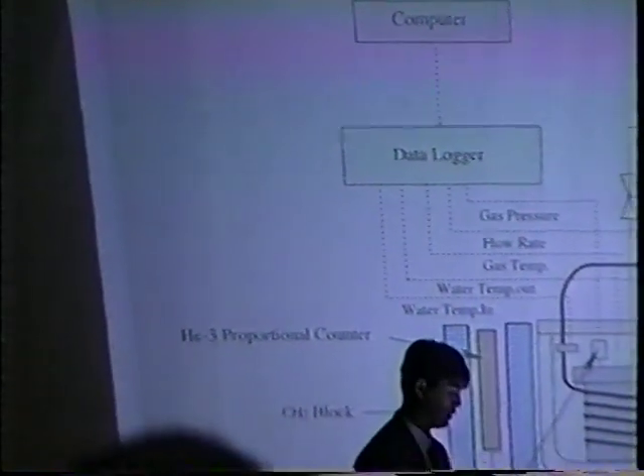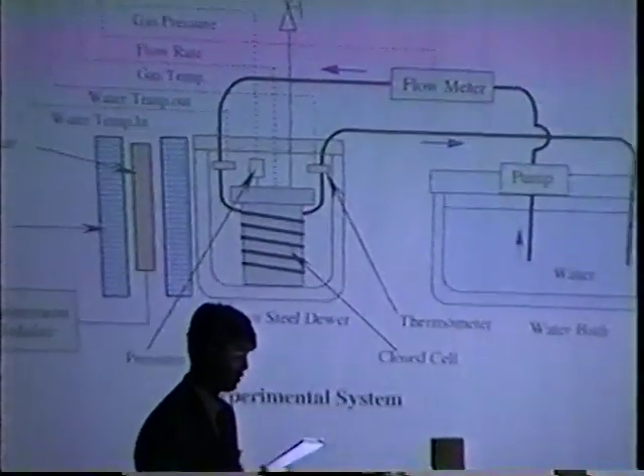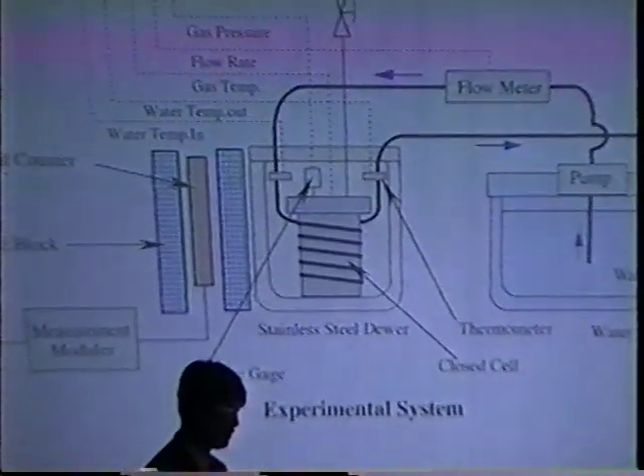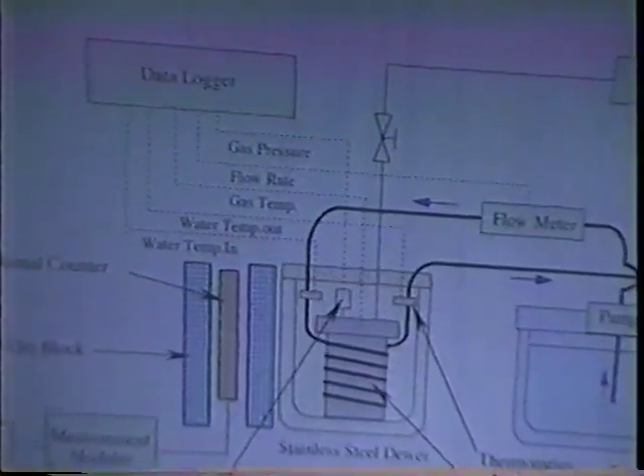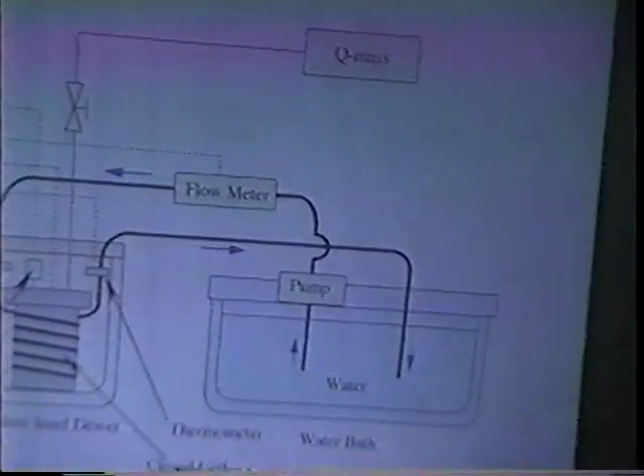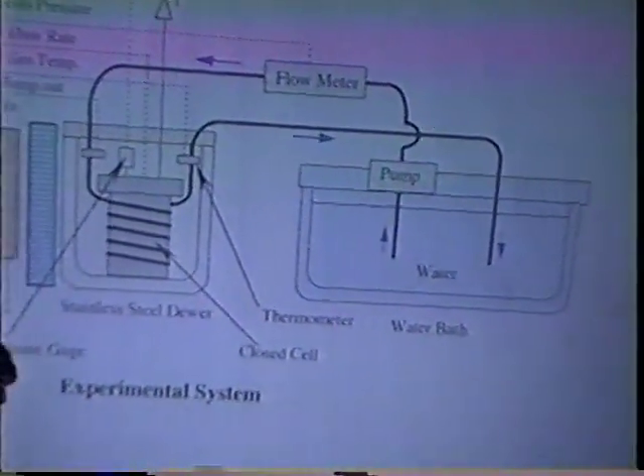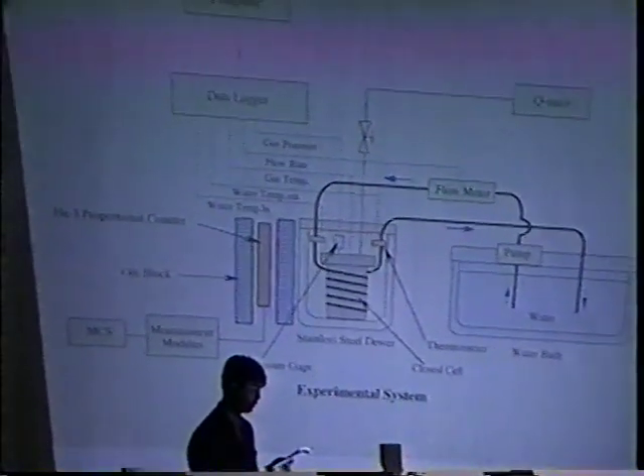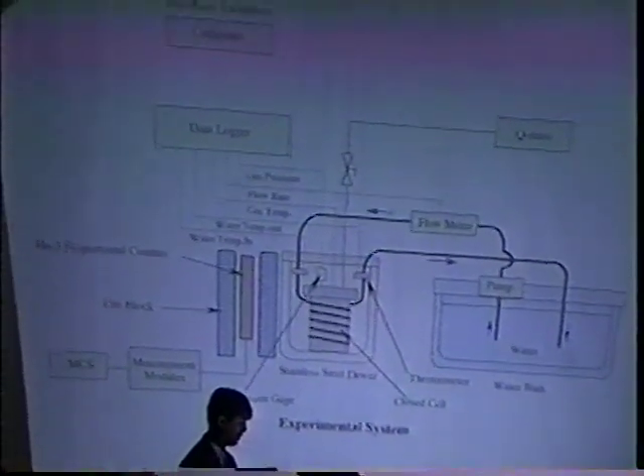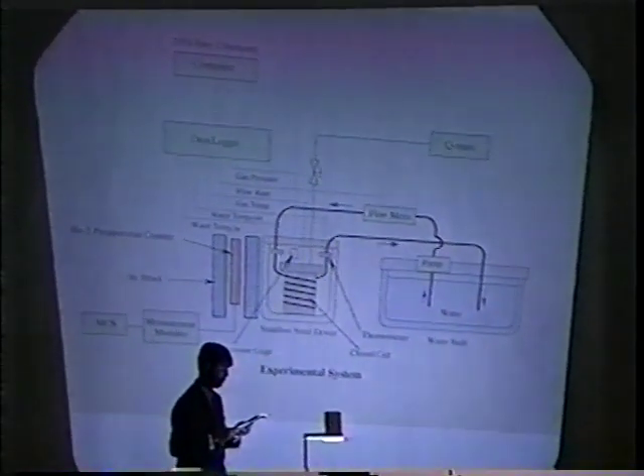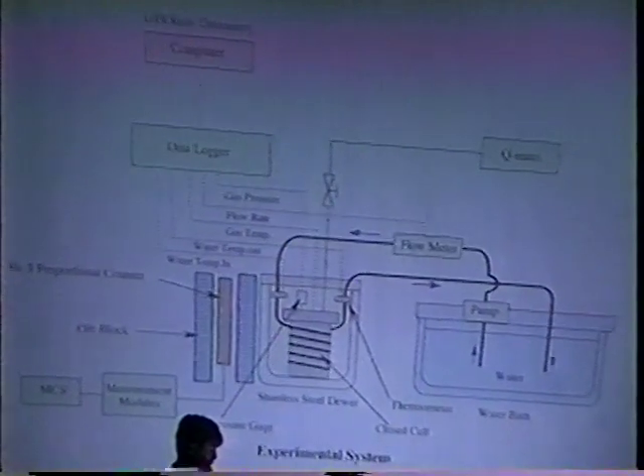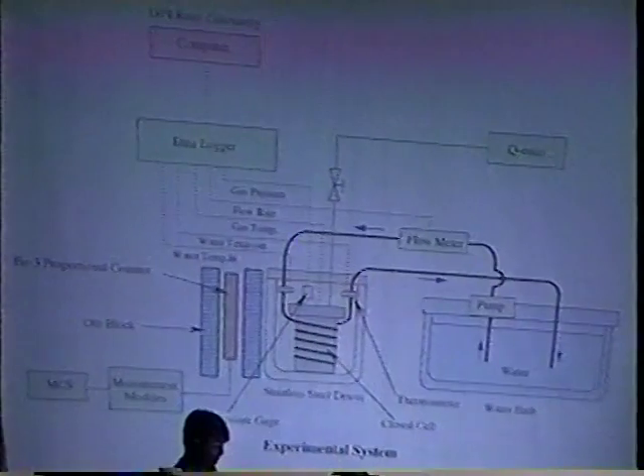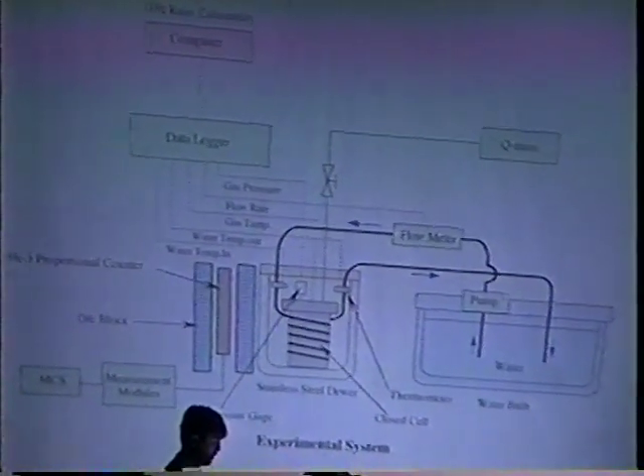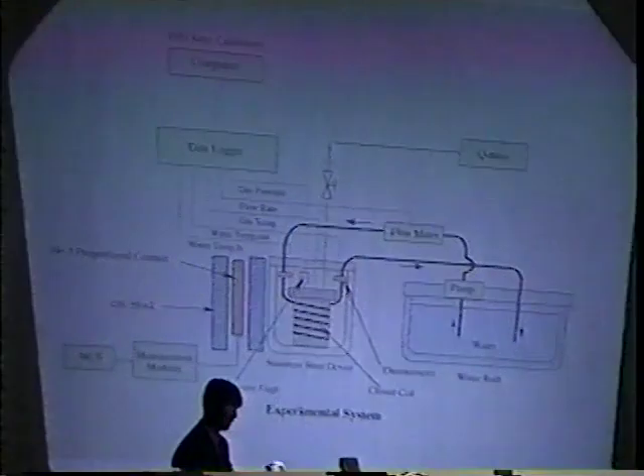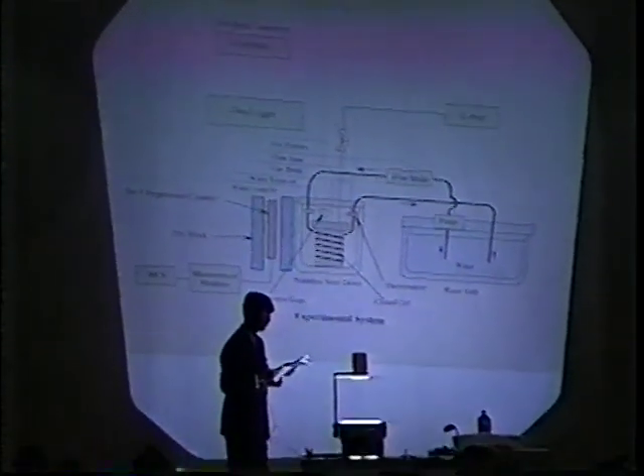This is the experimental system using the closed electrolysis cell. The cell was put in a stainless steel dewar to insulate it from heat from the outside. The cooling water was pumped from a thermal control bath, which is controlled with plus or minus 0.1 Kelvin accuracy, circulated in the cooling pipe through a flow meter, and discharged to the bath. A helium-3 proportional counter is set up inside polyethylene blocks beside the dewar to detect neutrons.